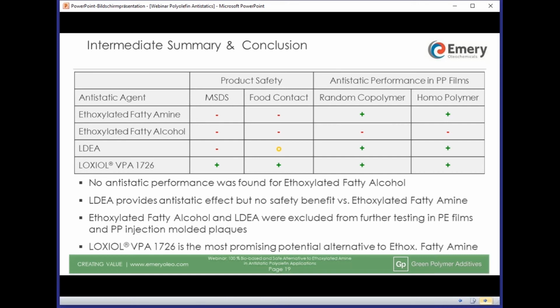What about LDEA? It works well, yes, but would you use it to replace ethoxylated fatty amine? Where would be the crucial benefit? You would replace a material which is not safe by another material which is not perfectly safe too. That is why we excluded LDEA from further testing as well, and only compared ethoxylated fatty amine and LOXIOL VPA 1726. So far, LOXIOL has proven to be a safe material that can compete with the amine performance-wise. Hope you are curious to see further results.